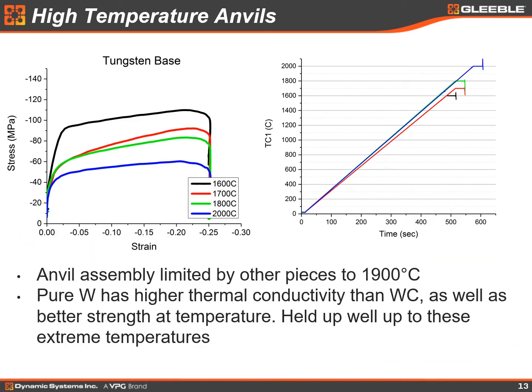So we switched to running tests with pure tungsten as the anvil base. As I mentioned, it has a higher thermal conductivity than the tungsten carbide, meaning it probably saw much lower temperatures than the tungsten carbide bases saw, as well as having just better stiffness at temperature overall. Several tests were again run up to 2000 Celsius, and the anvils and anvil bases were no worse for wear. On the other hand, some of the other parts of the setup melted at these temperatures, so I think 2000 Celsius is going to be our current limit for this new ultra high temperature anvil material.